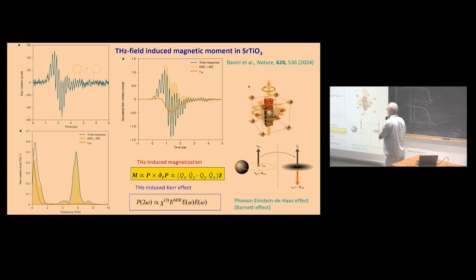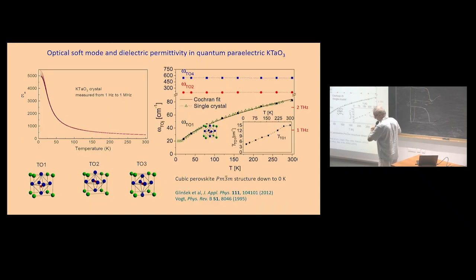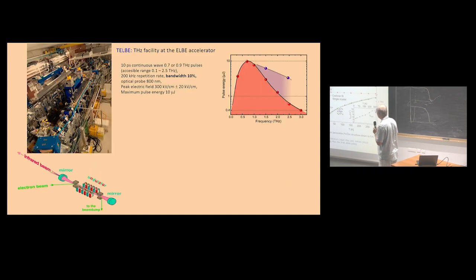But it is not exactly seen directly, and the problem is that this 3 terahertz pump is quite broad. We decided to measure potassium tantalate because it is cubic down to the lowest temperature. It is very similar to strontium titanate. Again, permittivity is growing at low temperatures, and we can come to resonance with the soft phonon. This increase of permittivity is due to phonon softening. And so we pumped this phonon at low temperatures.